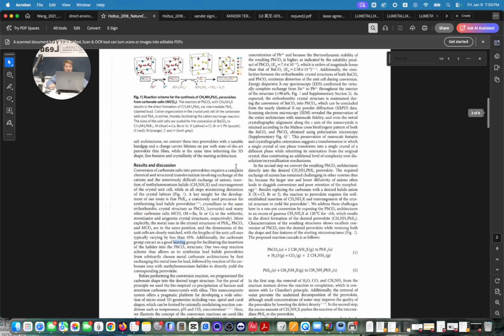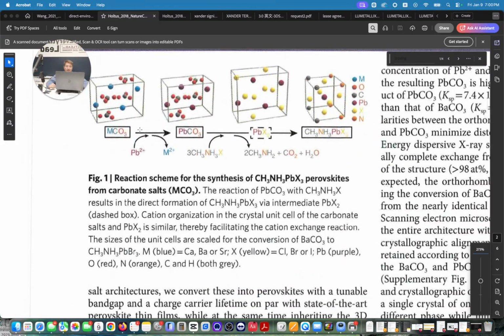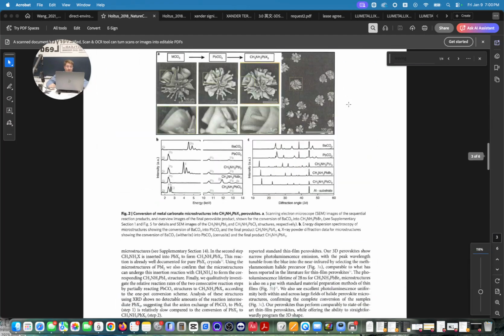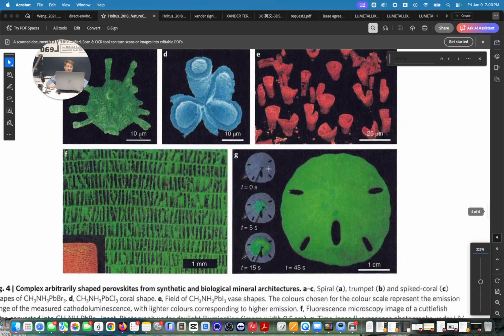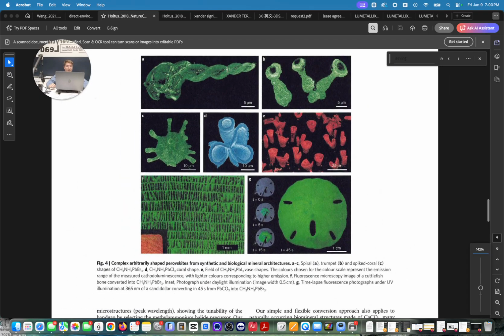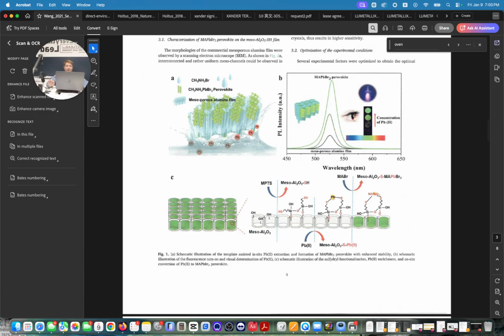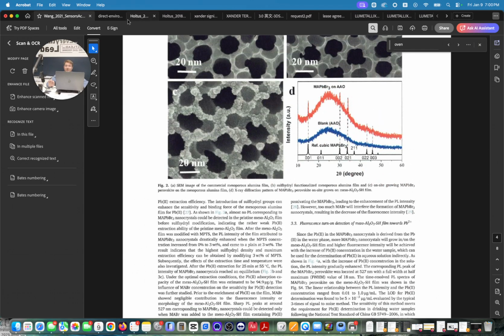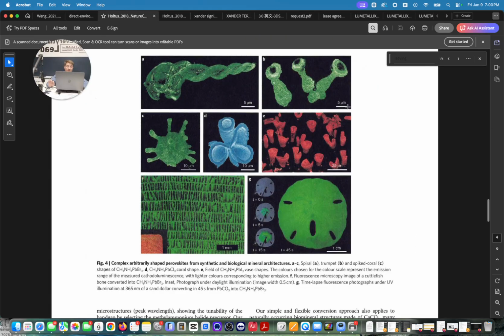So these folks essentially took a calcium carbonate surface, they added lead to it, and then they reacted it to form the perovskite. And so we can see that is the case here. And it was pretty cool research. They took a sand dollar, they took a cuttlefish bone, and then they had synthesized these tiny nanocrystals. And now these are not nearly as small as those mesopores from the Wang et al. paper. You can see that these are only 20 nanometers in diameter, whereas these are much larger. So this is 5 micrometers, this little thing here, and much larger. You wouldn't barely even be able to see the nanopores. That's how small they actually are.